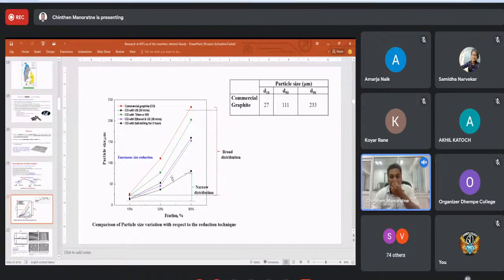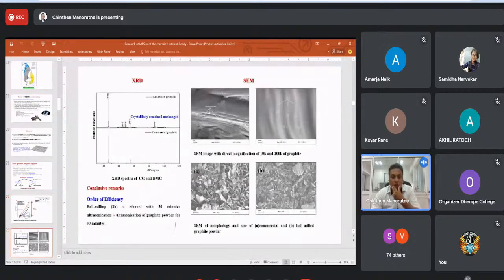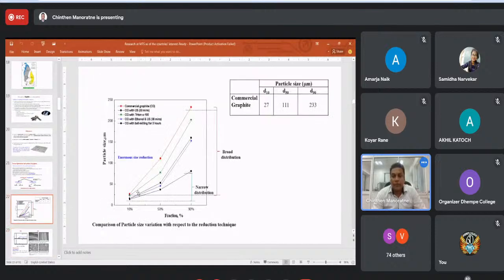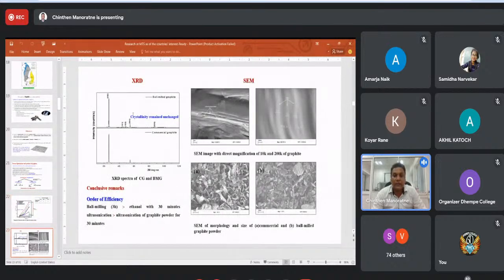Like that, we have found that ball milling for 3 hours is sufficient to obtain maximum particle size dispersion, followed by ethanol for 30 minutes, ultrasonic, etc. Now this graph shows the crystallinity has not been disturbed because of this ball milling, because the XRD spectra obtained for the ball mill graphite and commercial graphite are almost the same.